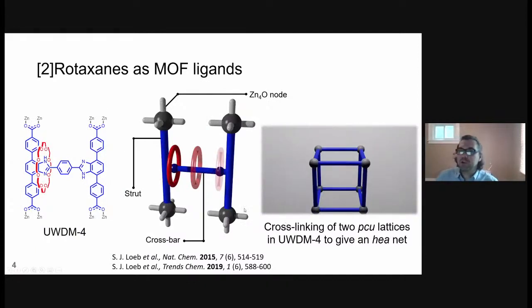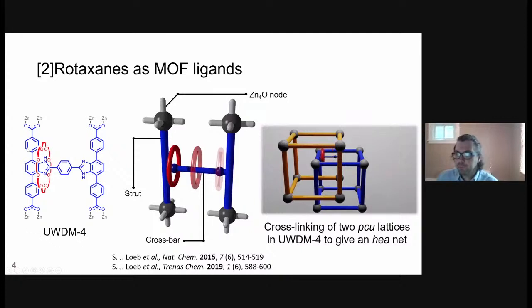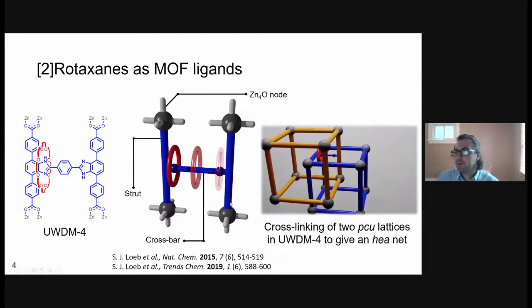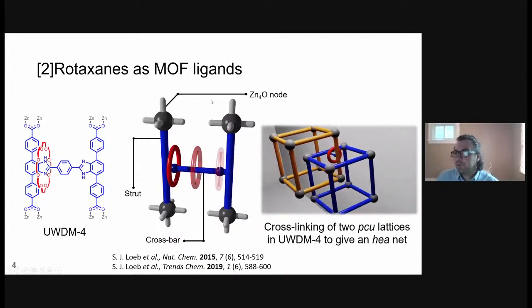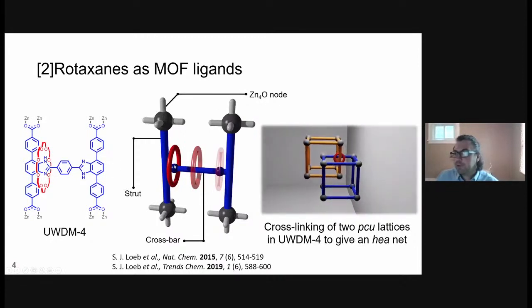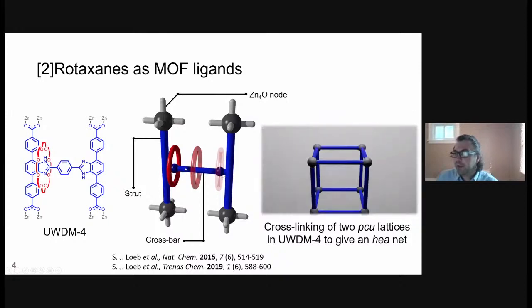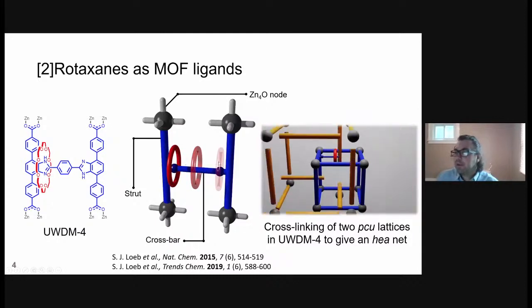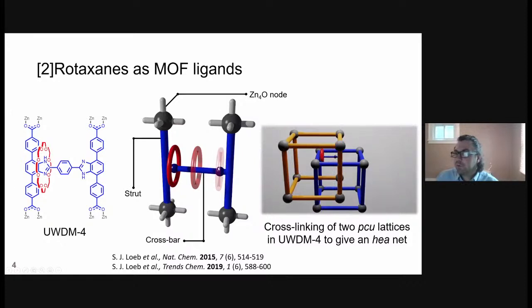So in terms of how we can actually go about building MOFs with these types of rotaxane linkers, one strategy is known as the cross-linking approach. And this is what was used in UWDM4. We took this H-shaped axle here, and each of these sides we refer to as struts. They each formed with these zinc nodes a pcu lattice, and these pcu lattices were joined by this crossbar here. So overall, this gives an hea net. And along this crossbar, we have these two recognition sites, and this is where we see the shuttling of this macrocyclic ring.